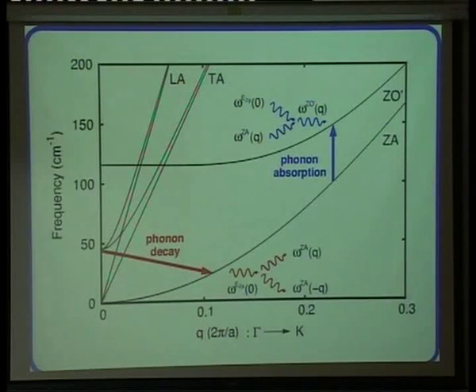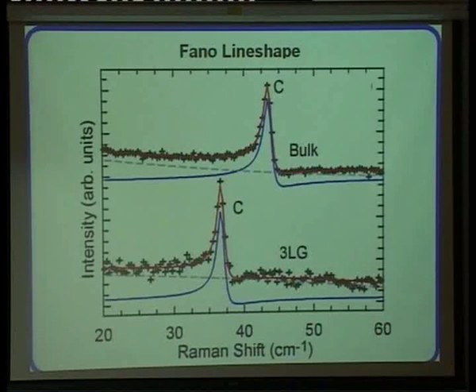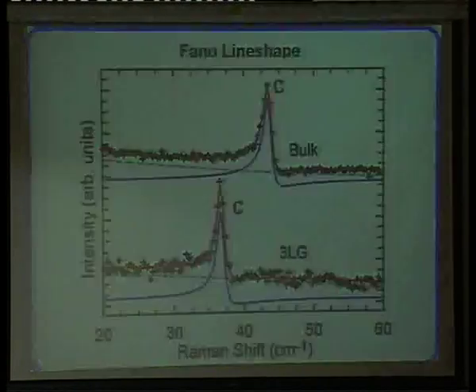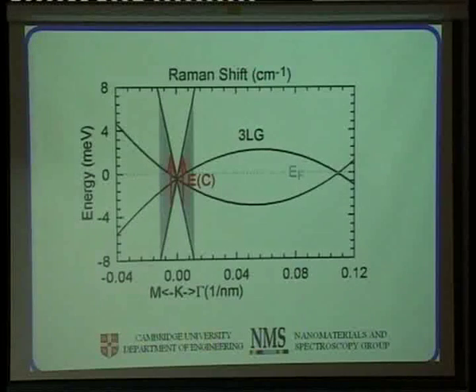The other thing is when we look at the detail of this peak. So, for example, the full width. The peak can decay by phonon absorption or by electron-phonon coupling. And in fact, what we see is that this peak has a Fano line shape, and the energy here is quite small, of the order of milli-electron volts. So we argue that we have actually a Raman peak that is sensitive to electronic transition at very low energy,